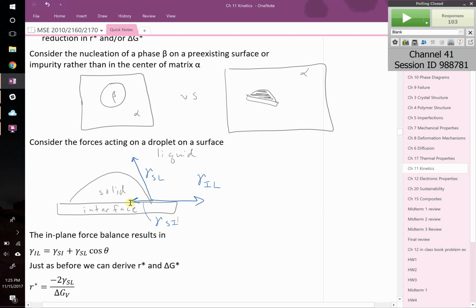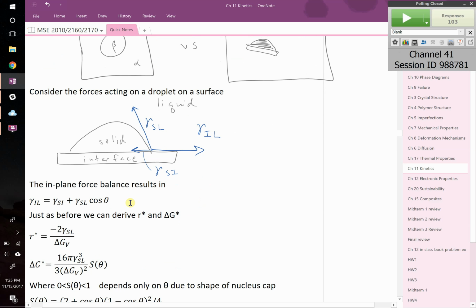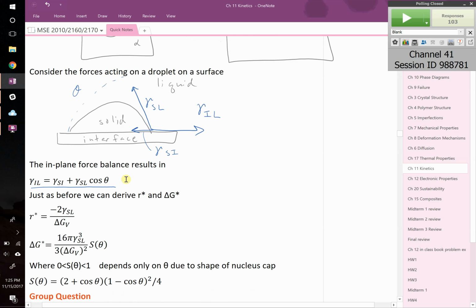You can sum these up and find that the in-plane force in the x-plane could be solved by this expression, where this angle right here is your wetting angle. That's theta, what we call the wetting angle. So if you know the wetting angle, that allows us to modify these expressions, and here's how it does so.